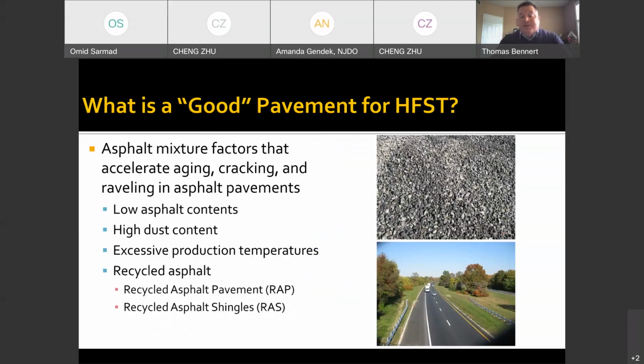We have some situations in asphalt where low asphalt contents, high dust contents, excessive production temperatures from the plant, or an overuse of recycled asphalt that isn't used responsibly, you can actually get yourself into a situation where a newly constructed pavement that appears to be good would not be a good candidate for HFST. That picture on the right is a prime example.